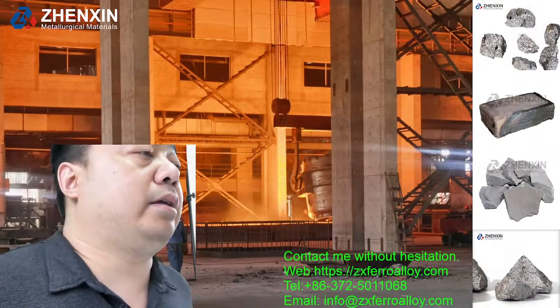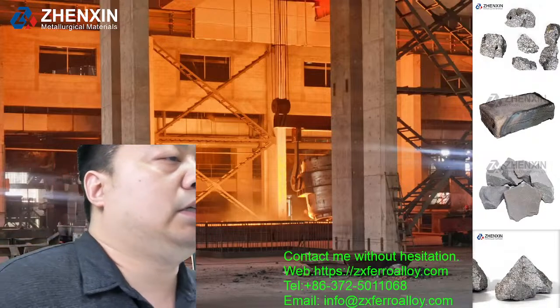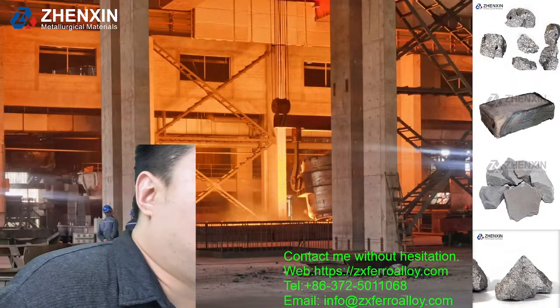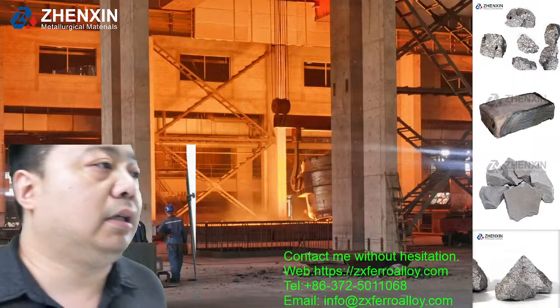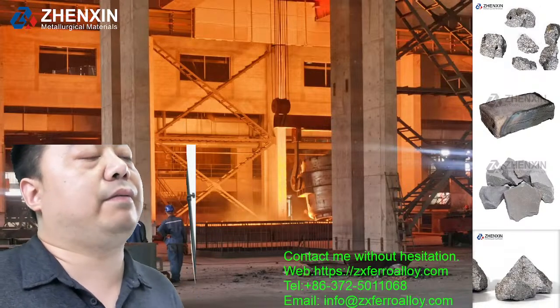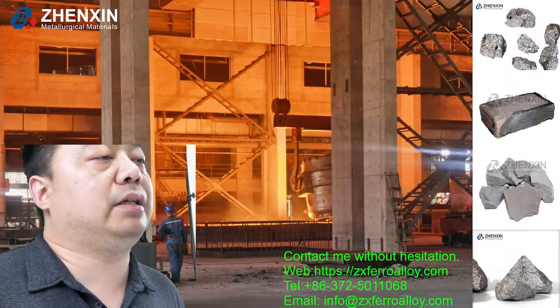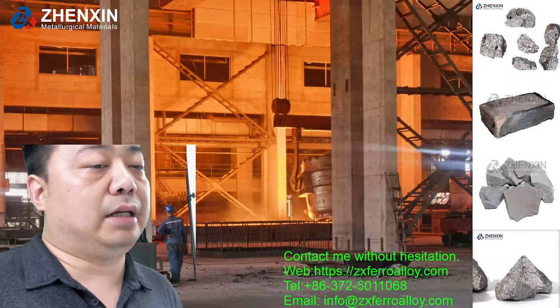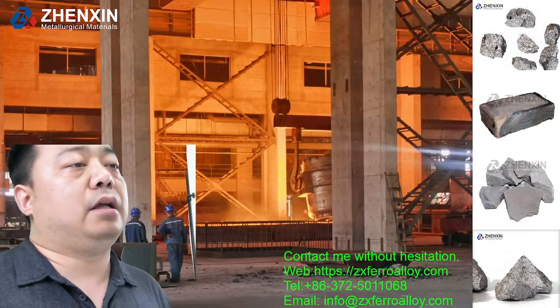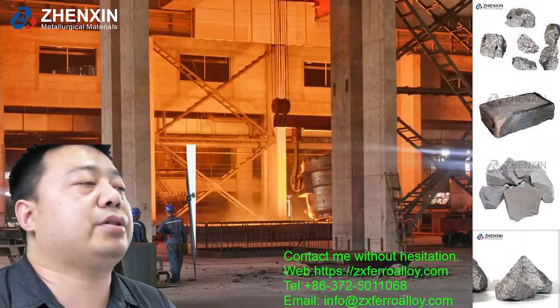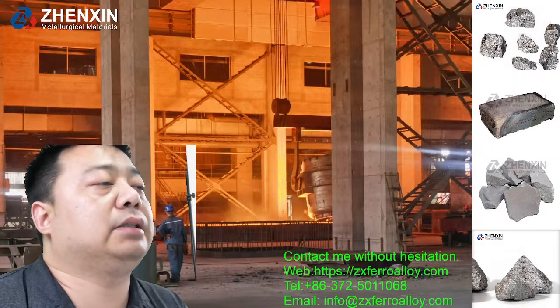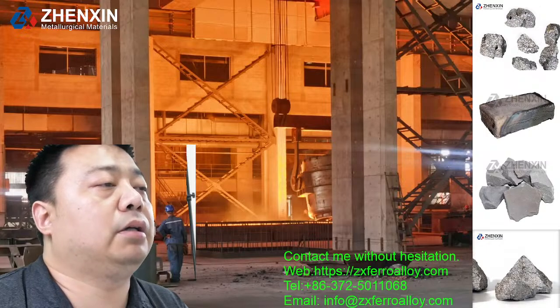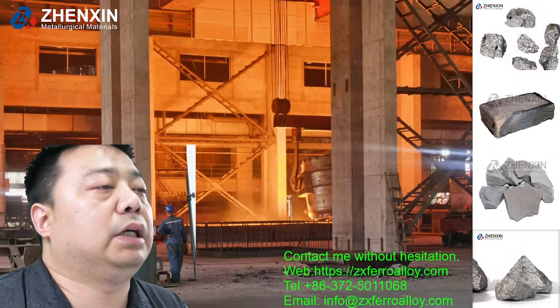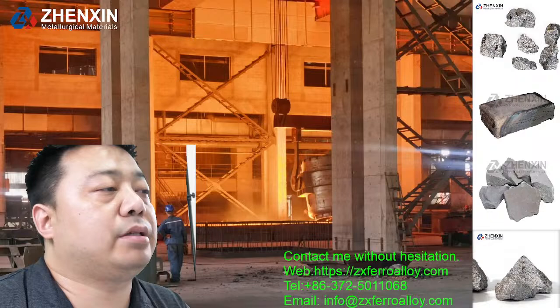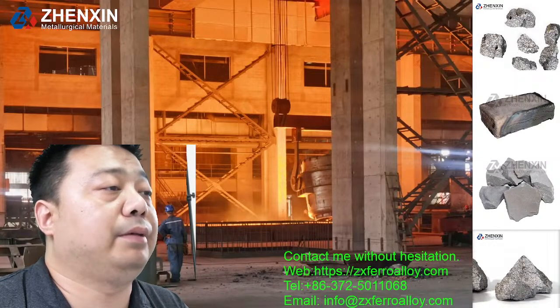Research shows that the role of nitrogen in expanding the austenite region is about 13 times that of nickel. At present, adding nitrogen to the production of nickel containing austenitic stainless steel can partially replace the precious natural nickel and bring considerable economic benefits. Also, nitrogen can make steel have high strength and high corrosion resistance and can maintain the plasticity of steel at a good level.